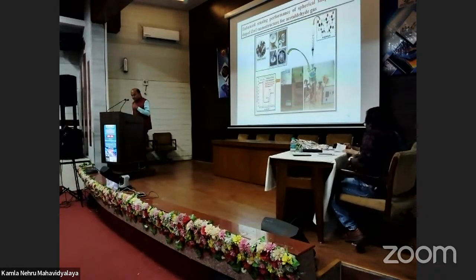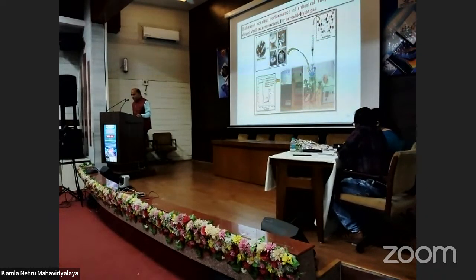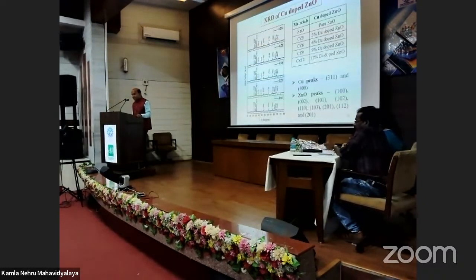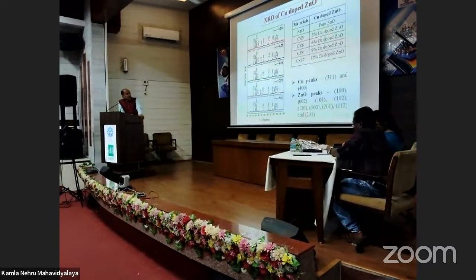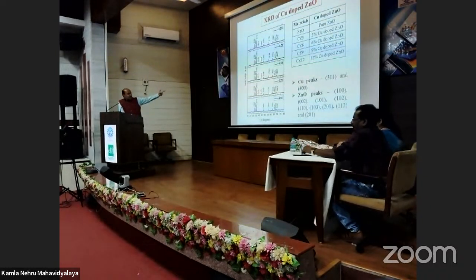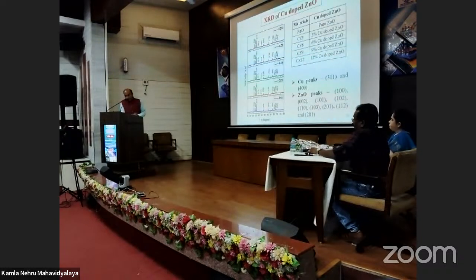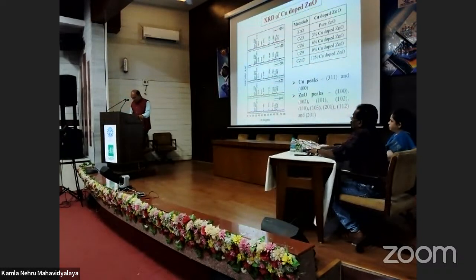Another is copper doped zinc oxide nanostructure for acetaldehyde gas sensing. These are the XRD patterns for copper doped zinc oxide. If you look into this, copper shows 2 additional peaks, that is 311 and 400. With doping from 3%, 6%, 9% to 12%, the 2 additional peaks are observed compared to pure zinc oxide.